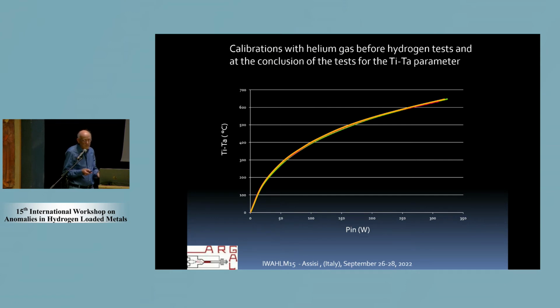We take this parameter, subtracting every time the ambient temperature, just to eliminate the influence of ambient temperature changes. And you can see that the internal temperature for calibration, all the curves up to 700 degrees, they overlap quite well.